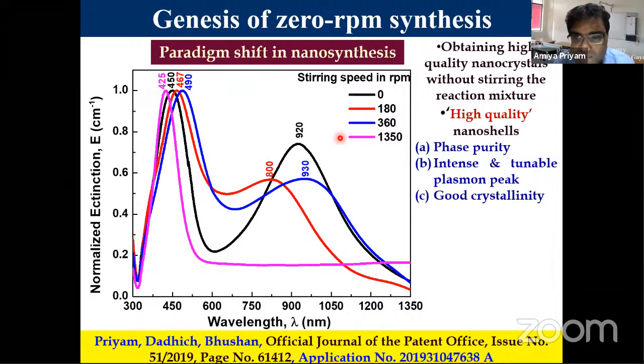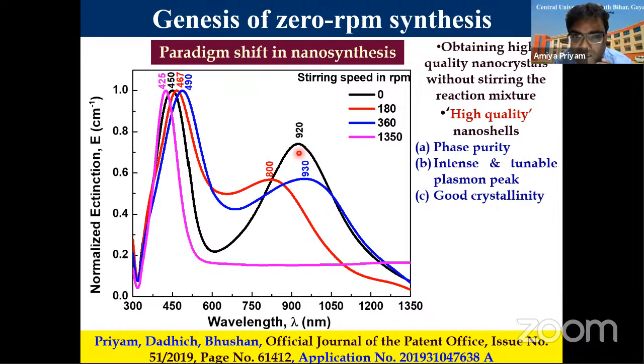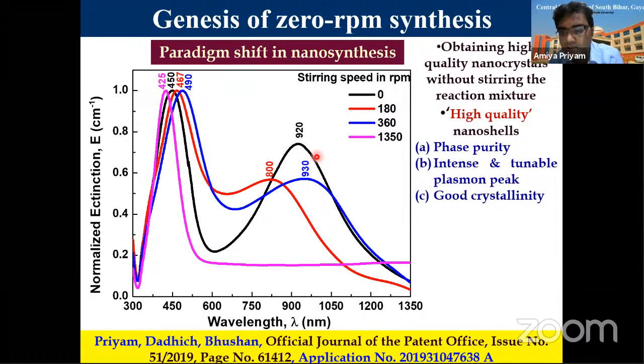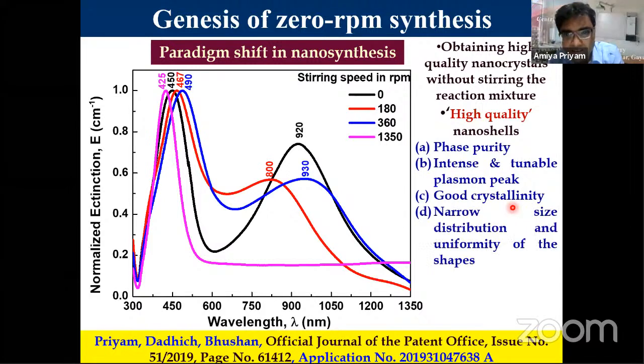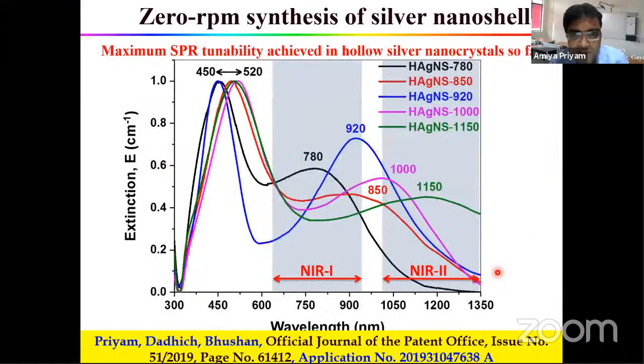When I say high quality nanoshells, the identifying features are phase purity, for which we have done XRD; intensity and tunable plasmon peak, where you can see the maximum tunability we have got; and enhanced intensity. As I showed you in some previous examples of published papers, when they go into the near IR region, the peaks were not good. They were typically broad. Here we are getting very intense peaks, and FWHM is less. Good crystallinity is there, which was verified by HRTEM imaging. Narrow size distribution and uniformity of shapes, all of this was there.